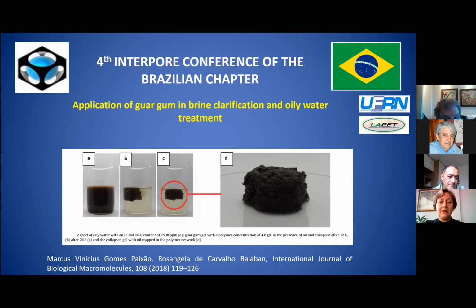So in this slide, we are showing the application of guar gum in brine clarification and oil water treatment. Guar gum is a polysaccharide extracted from seeds of leguminous. So this polysaccharide was cross-linked through borate ions. And in the first picture, we can see oil water of a high salinity that was submitted to guar gum gels. So we added guar gum with borate ions.